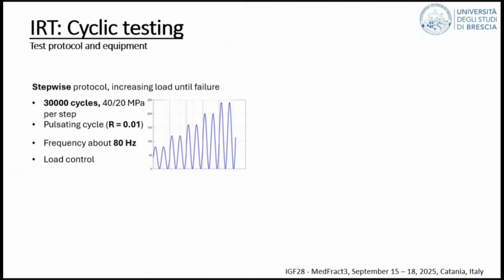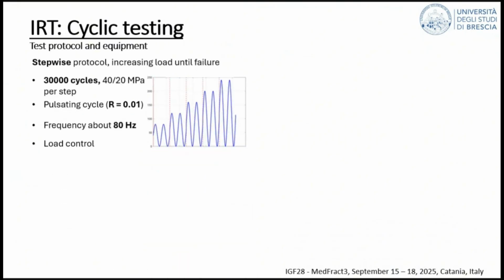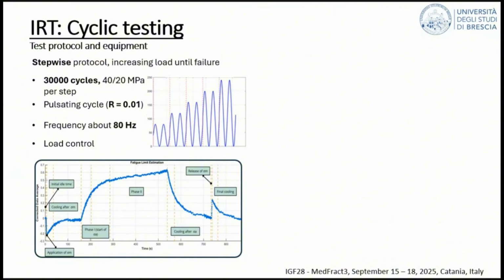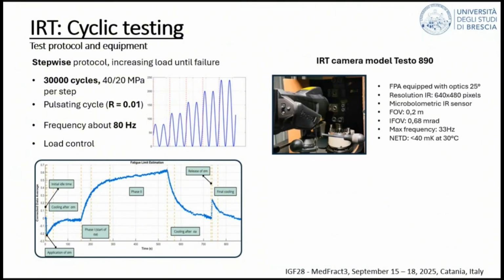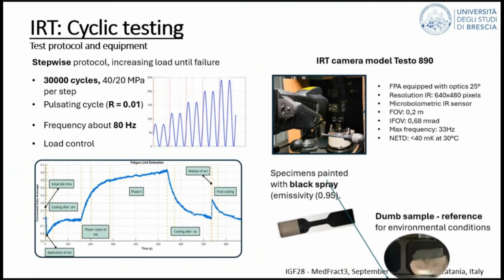Now, moving to the tests that we carried out in this research, we adopted a so-called stepwise protocol. We had the sample and we applied sequences of block loading consisting of 30,000 cycles. The load was increased up to failure. This is an example of the type of curve that we obtained from the testing. And these are just some details about the setup.